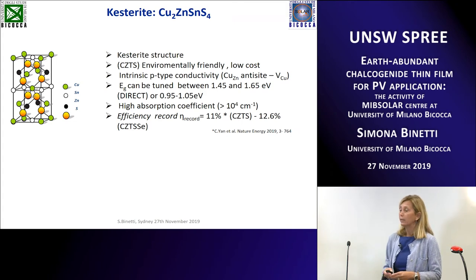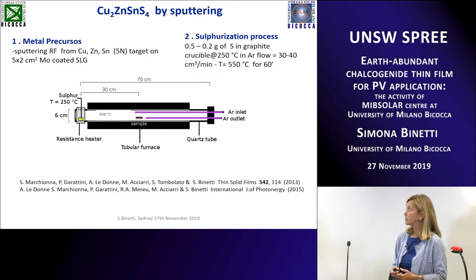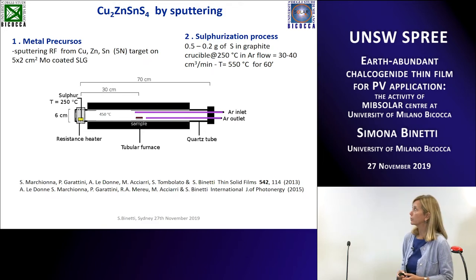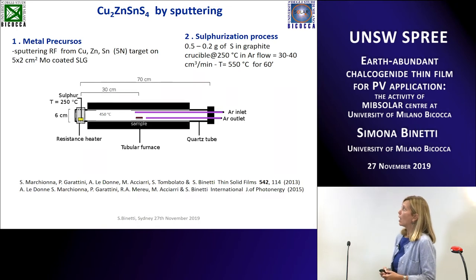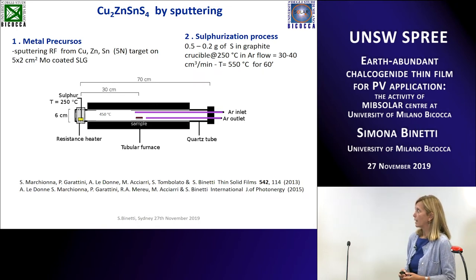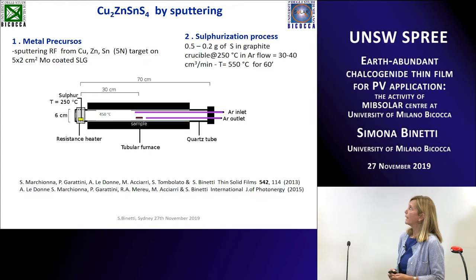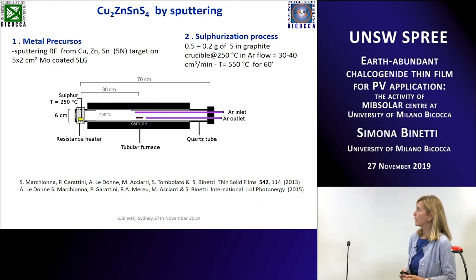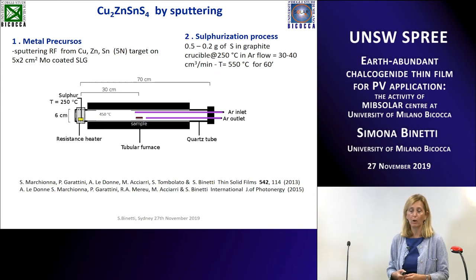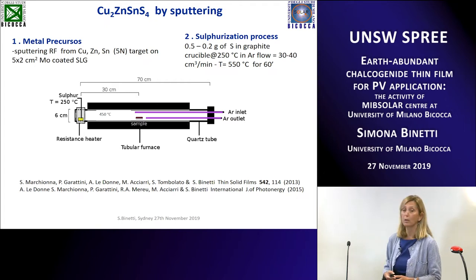We started with the classical two-step approach, by radio frequency sputtering of the metal precursors from three different high-purity targets of copper, zinc and tin on classical soda lime glass coated by molybdenum. And then we perform a sulfurization, but avoiding H2S because it's a toxic gas and we don't want to use it, and just using a sulfur atmosphere from sulfur powder.